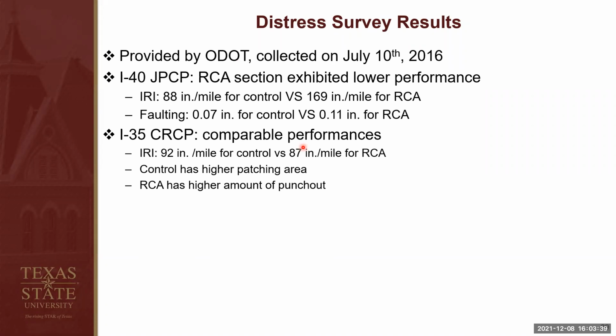We also had survey data from Oklahoma DOT, and the survey data were collected by Oklahoma DOT on July 10th, 2016. So we got international roughness index data. We also had faulting and punch out data for the RCA sections and control sections. As you can see, the data had the same conclusion as from our FWD results. RCA section had a lower performance compared to the control section.